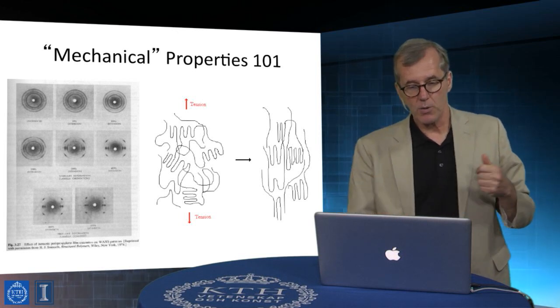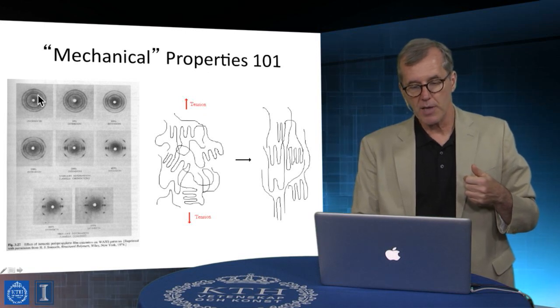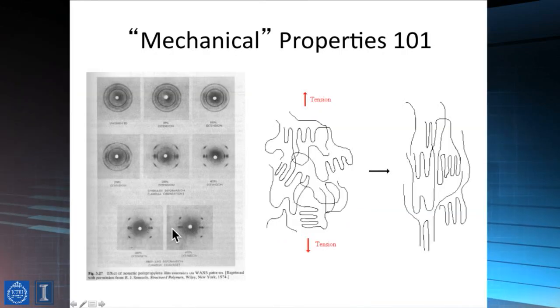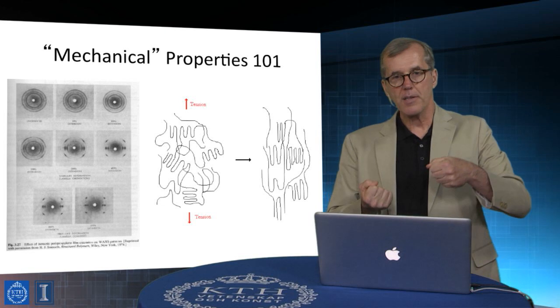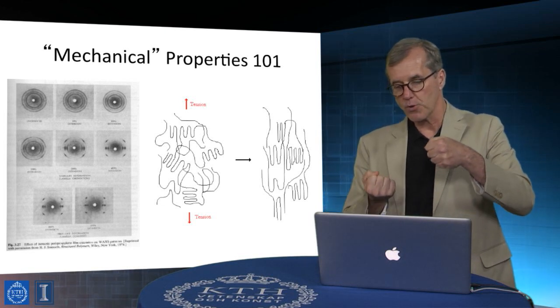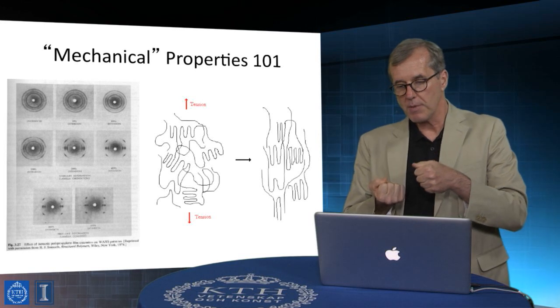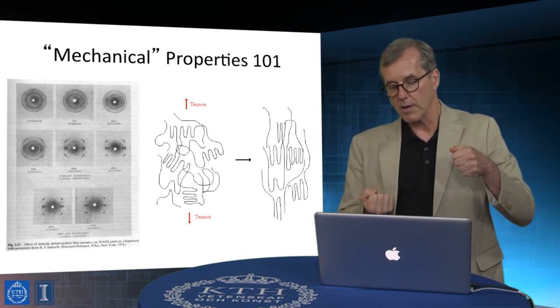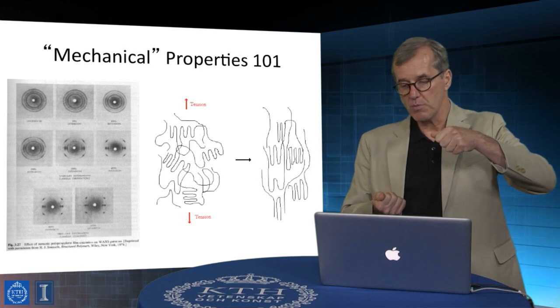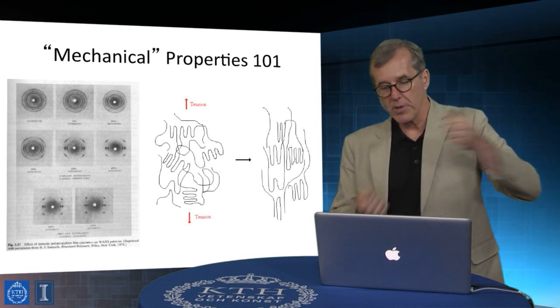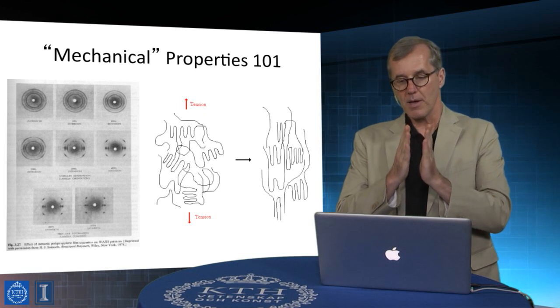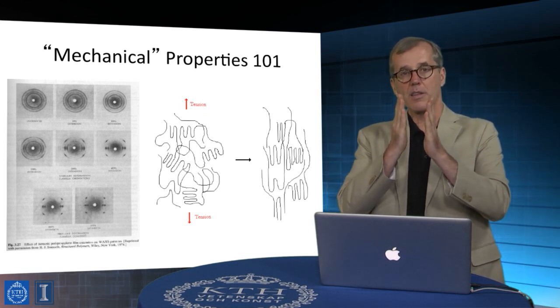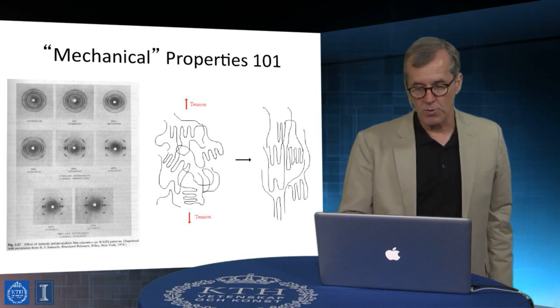And what you notice is that you go from essentially powder patterns in the X-ray patterns to highly organized reflections that correspond to elongation of chains and organization of lamellae. And in fact, these kinds of mechanically worked transitions in crystalline structure can be done to very high degrees of elongation. Essentially, you can pull these chains to the point where they're fully extended, and the lamellae form essentially an infinite length along the axis of the drawing.